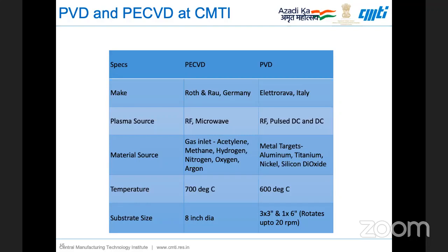We offer this for surfaces. Similarly, PVD has RF, pulse DC, and DC. You can have metal and even ceramic targets as well. It goes up to 600 degrees centigrade. It has about three 3-inch targets and one 6-inch target, with a rotation of about 20 RPM.